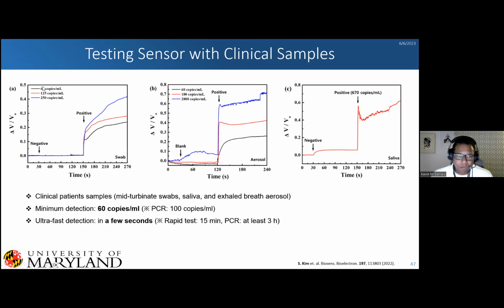And as you can see, we're able to detect down to 60 copies per milliliter, as opposed to traditional PCR, which is able to detect 100 copies. And we're able to get pretty high resolution, or high sensitivity, and quantitatively detect patient samples that are positive, as opposed to negatives, where we're not getting anywhere near above our noise threshold of 20% change. And it's faster and more sensitive than conventional tests. And all this is non-invasive, with the exception of the nasal swab.